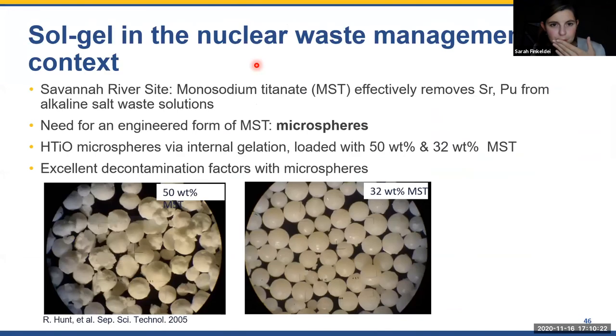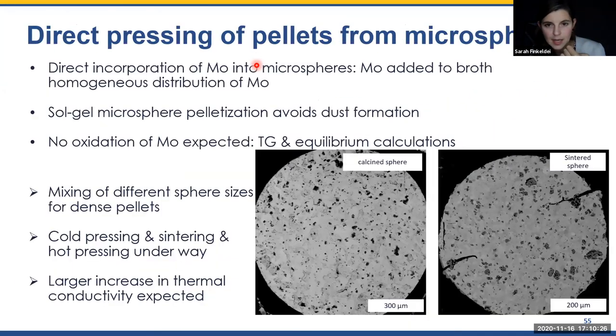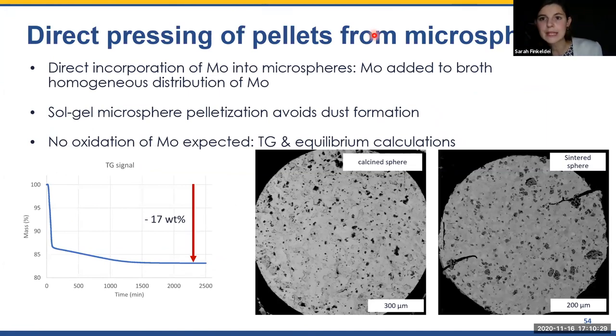Let me see, I think I have one more slide where this is shown. Here. So you can probably see this one. We actually added molybdenum powder to our feedstock, and this is a calcined sphere. This is a cross section through a calcined sphere where you can see all the molybdenum distributed in it. Then we can mix microspheres of different sizes and therefore get a very dense packing, and then fabricate a pellet by cold pressing and sinter those materials. This did not lead to super high density, so at the moment we are trying to hot press the material to get a very high density. So this is not a cross section of a pellet. This is just of a single sphere of those microspheres.